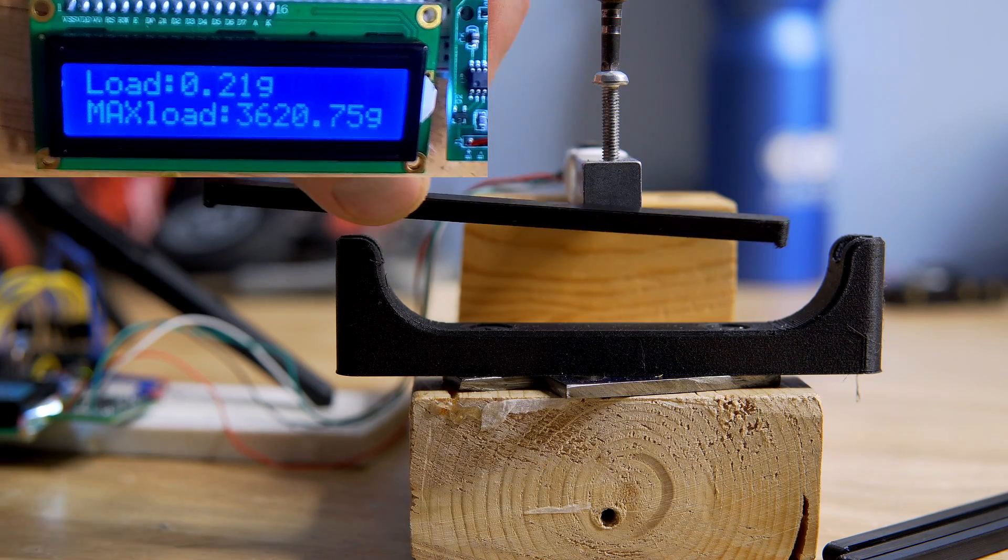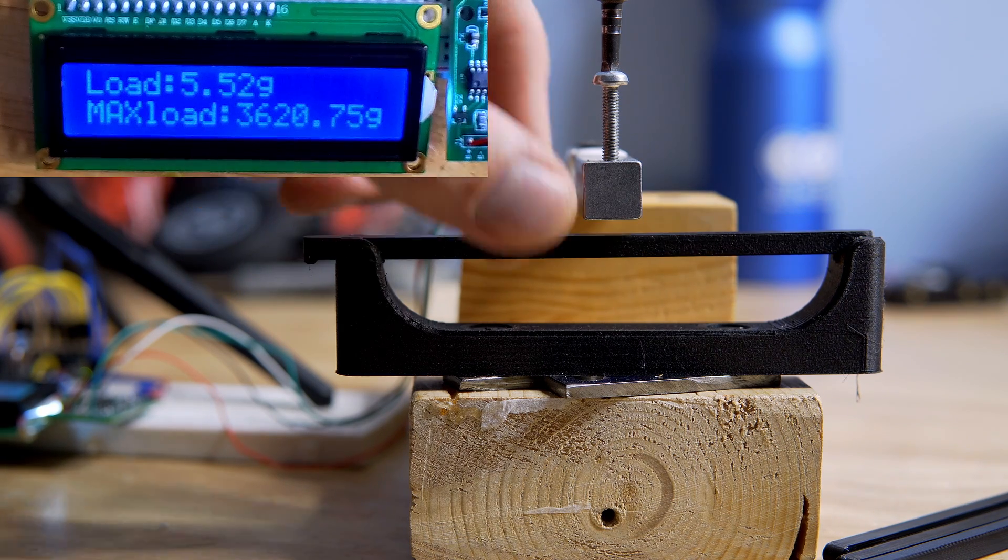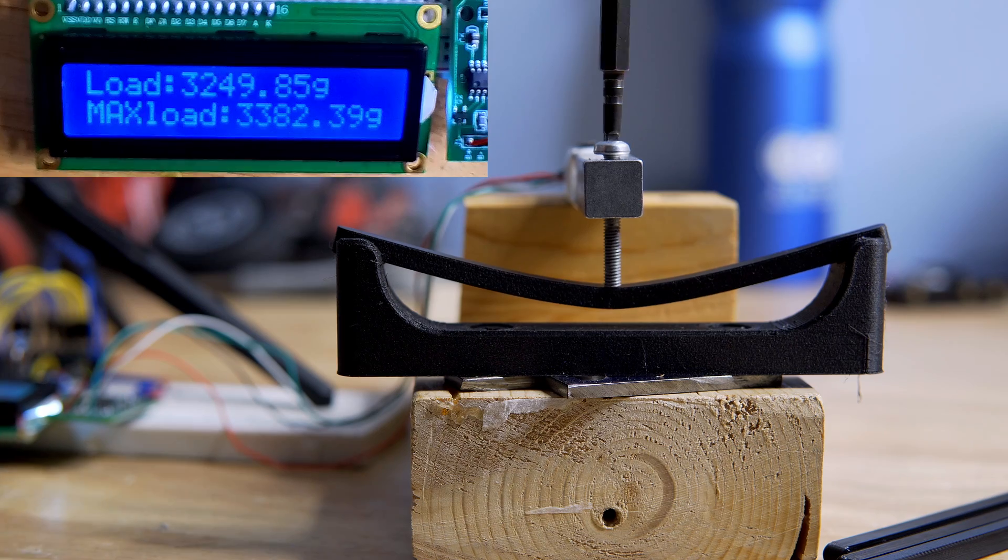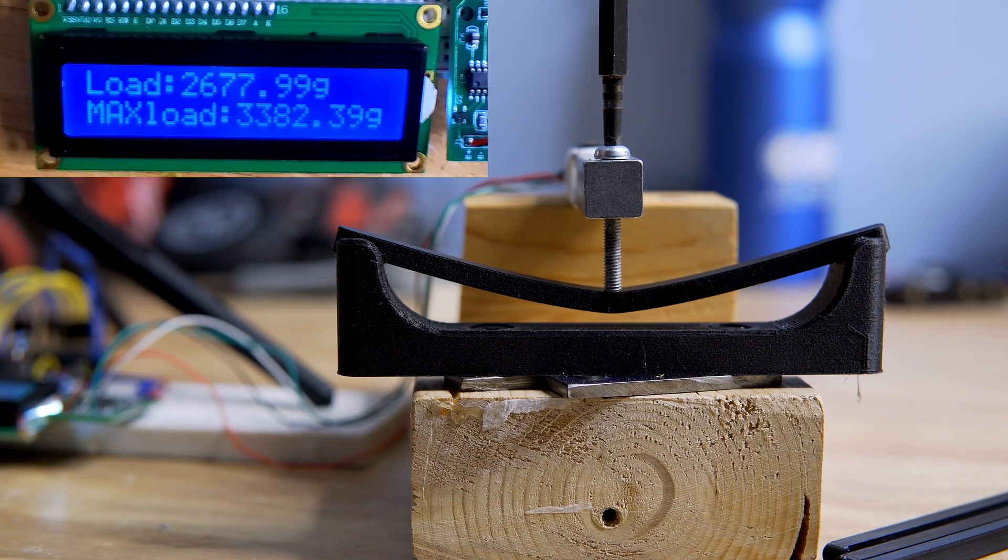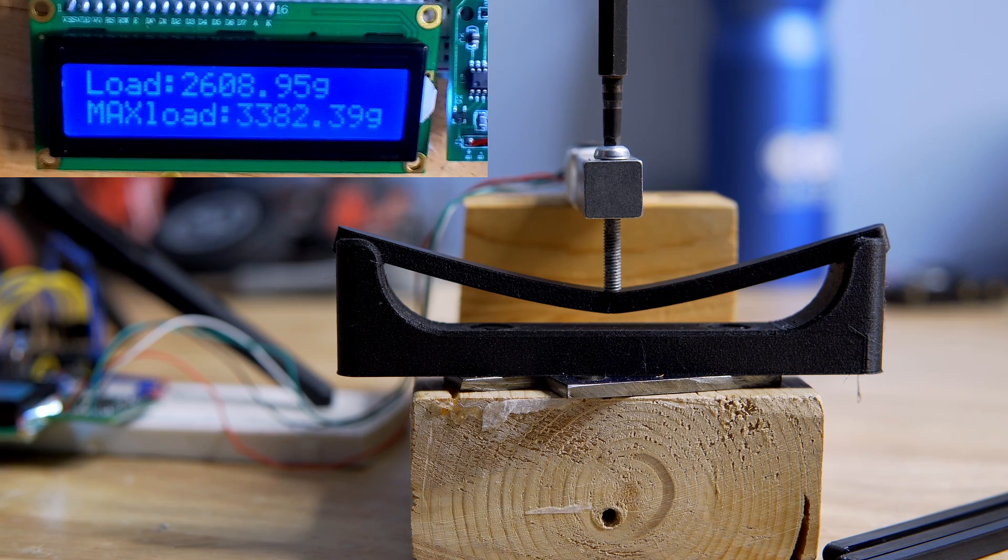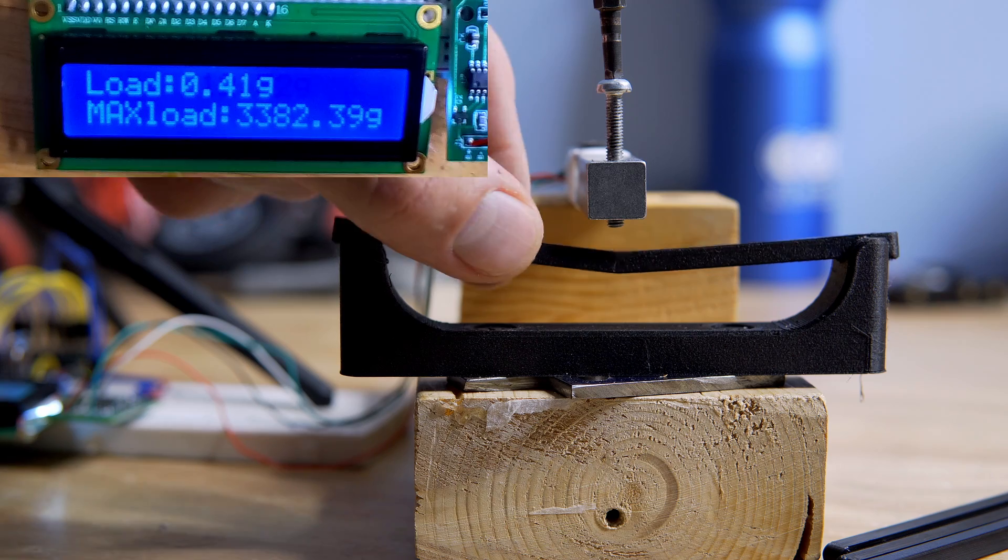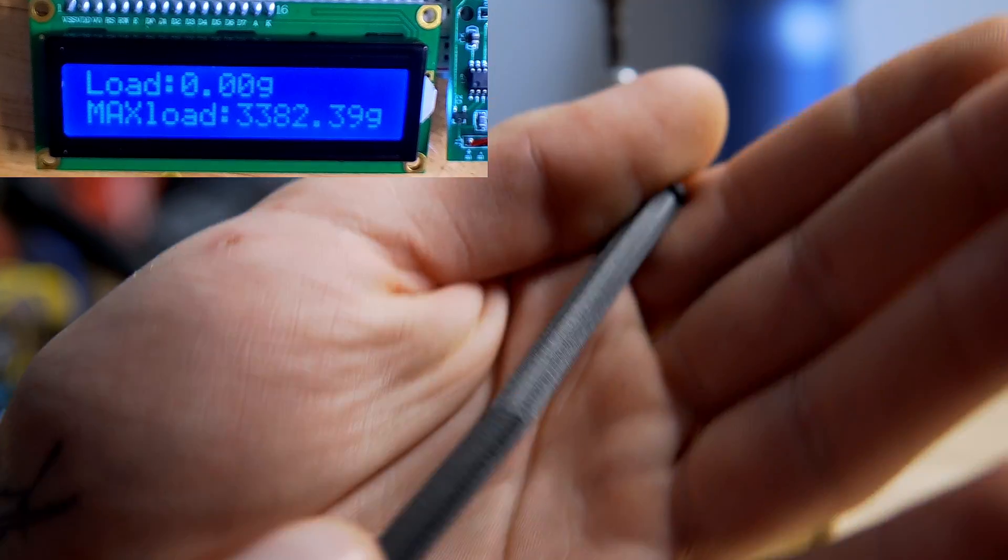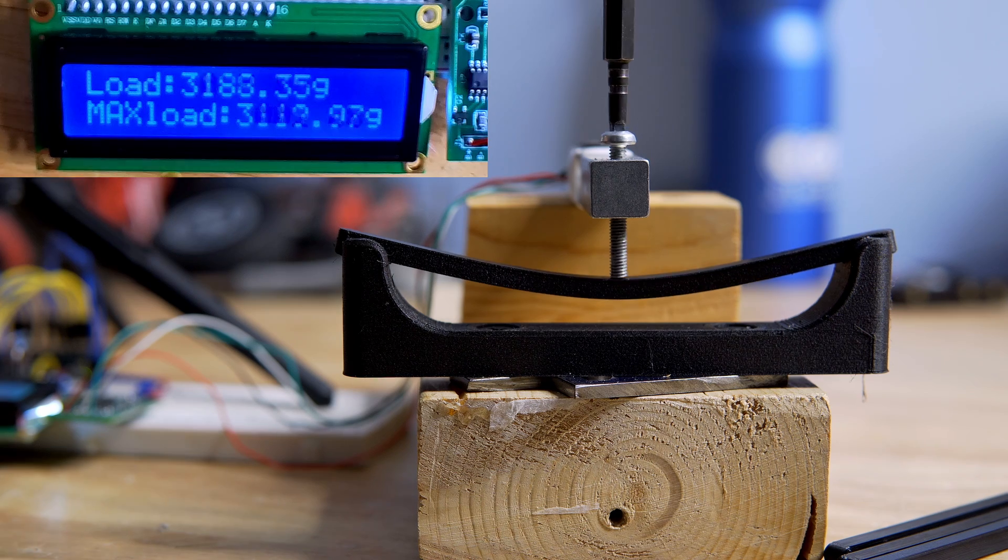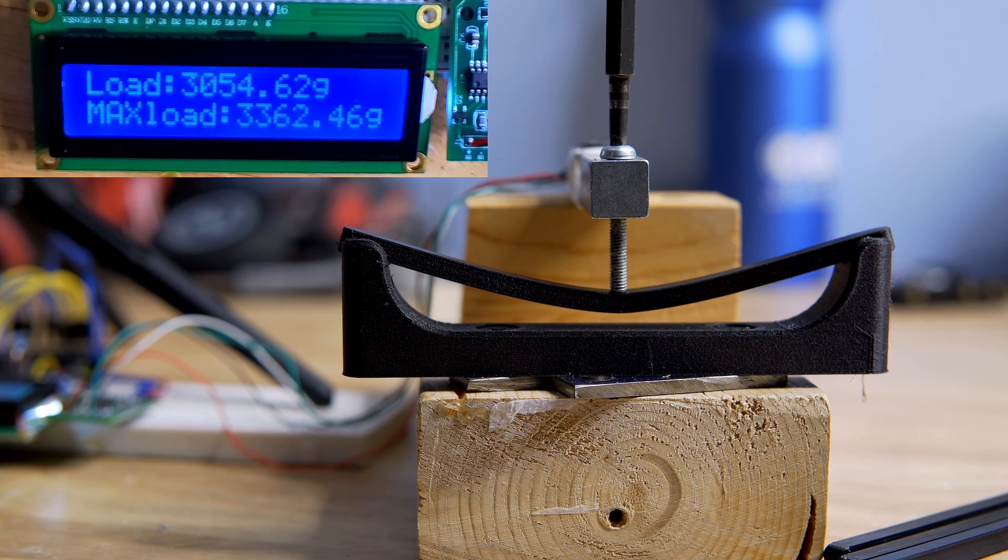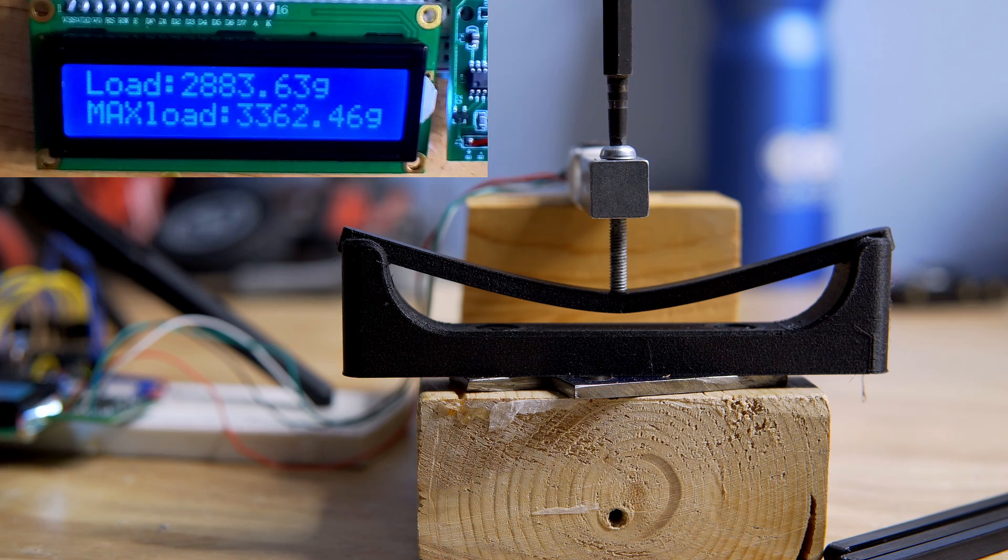Another carbon fiber PETG. Oh wow there's a crack. Okay. Wow that's low. We're at 3382 and there's a crack. And it did not return to its original position. There's a big old crack right there. Wow 3362 this time. And it looks like there is a little bit of a crack.